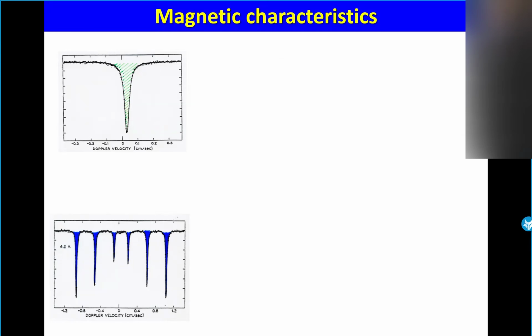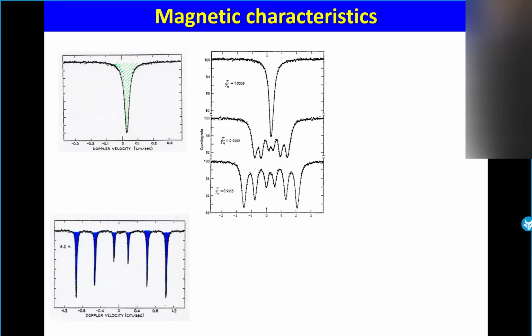Be clear. So, of course, if there is a change, we can look at the evolution versus temperature very close to the Néel temperature. And you can see that T over TN is 1.0009, 0.9989. That means within less than half a degree, you can see a dramatic change of the structure.